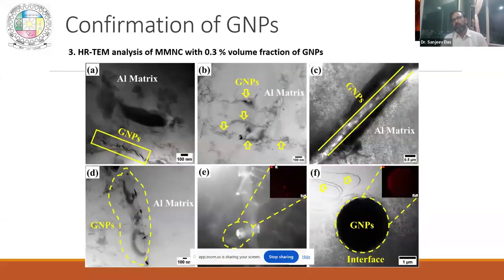Now this is TEM. Now people can say that you have taken TEM, so maybe the particles are there only, and it is not uniformly distributed. That could be a question. So what we did, we didn't do a lot of TEM, we just did 2 TEM samples from a big billet, very small samples. If it is uniformly distributed, from those 2 samples we will get the GNPs, and we found them in both the samples.